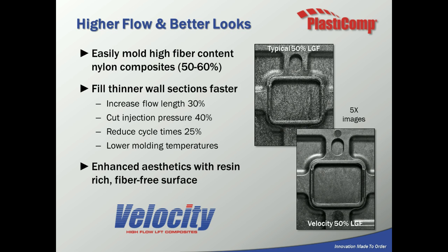But if you need to further improve it, we can go to a Velocity grade, which is a higher flow grade. It can increase flow lengths by 30%, cut injection pressures by as much as 40%, and may allow you to lower molding temperatures, which can reduce cycle times by 25%. If you look over on the right, the bottom right-hand corner is our Velocity grade at the same processing conditions compared to standard long glass materials, and you can see there's a big improvement in surface appearance with this product.